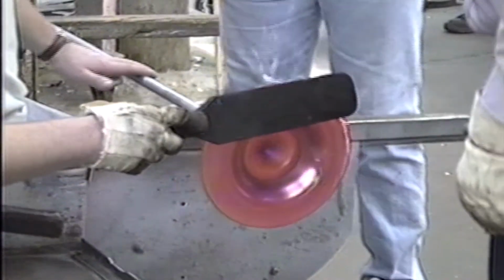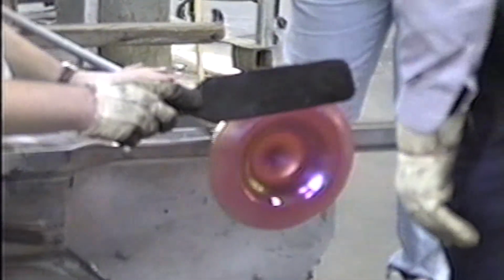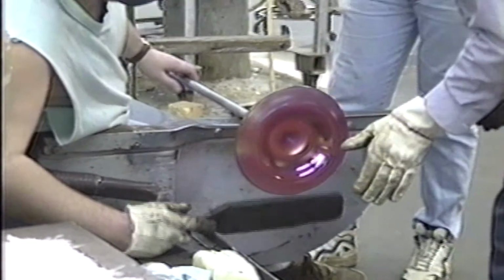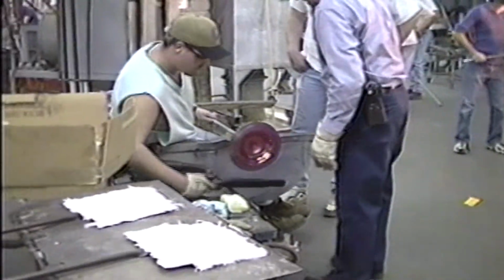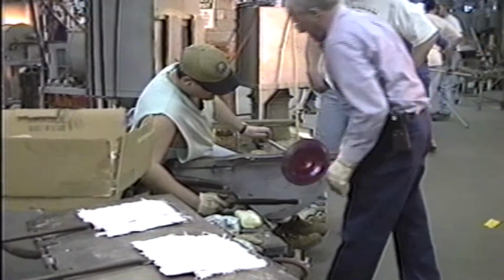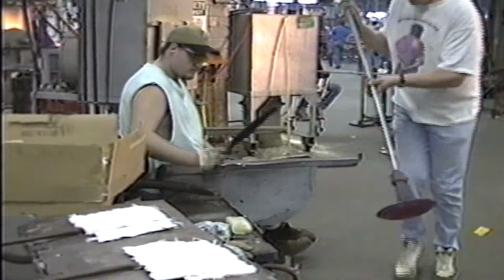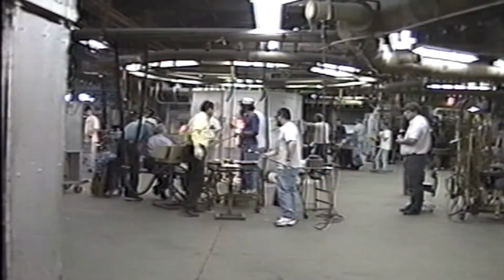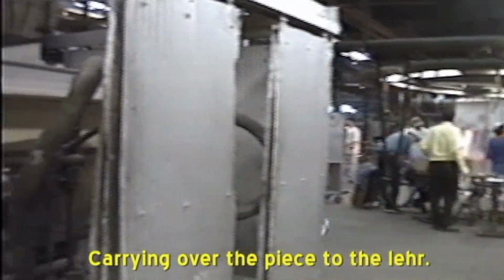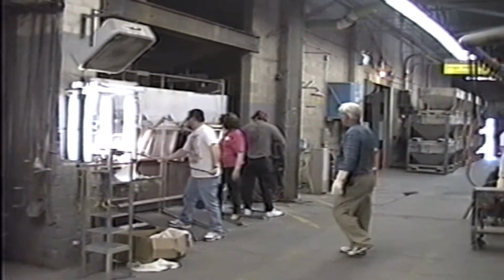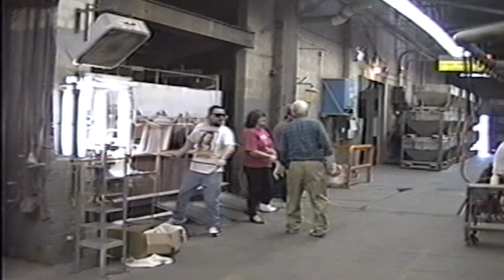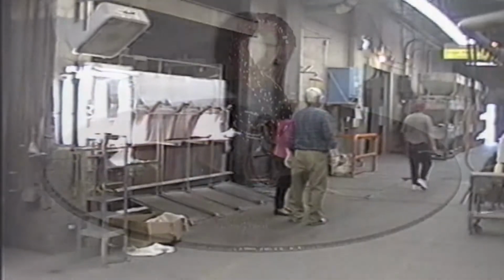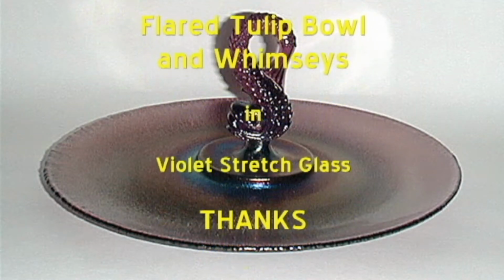And we weren't turning them back as far as the older ones were turned back. They would normally sit on the ring in the middle. I'm guessing that we probably had some that came away that were what we call rocky bottoms. They didn't sit flat, and we might have actually ground some on a wheel to make them flat. And again, they're carrying them over and putting them in the annealing lehr, which again starts at about 1100 degrees. On this piece, typically it's 2 hours. For a thicker piece like an animal, it could be 4 hours. They probably should have put this one on a 4-hour lehr instead of a 2-hour lehr.